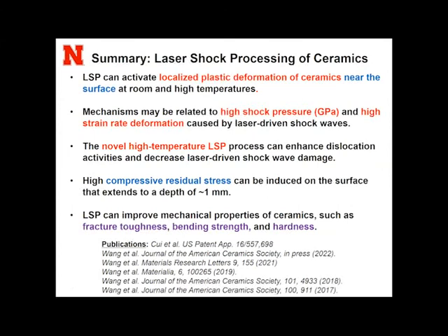So in summary, we found laser shock peening can activate localized plastic deformation in ceramics near the surface at different temperatures. The mechanism could be related to the very high shockwave pressure and high strain rate deformation. We have invented our novel high temperature laser shock peening process, which seems to be more effective than room temperature laser shock peening to decrease shockwave damage and enhance dislocation activity. In ceramics, similar to metals, we can also generate a high compressive residual stress, and the fracture toughness, strength, and hardness can be enhanced by laser shock peening. Below I show a list of some of our publications and patents. If you're interested, you can get more details of our work from these publications.